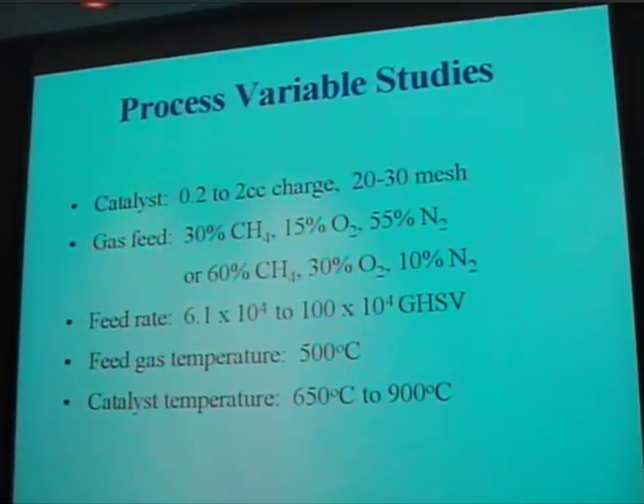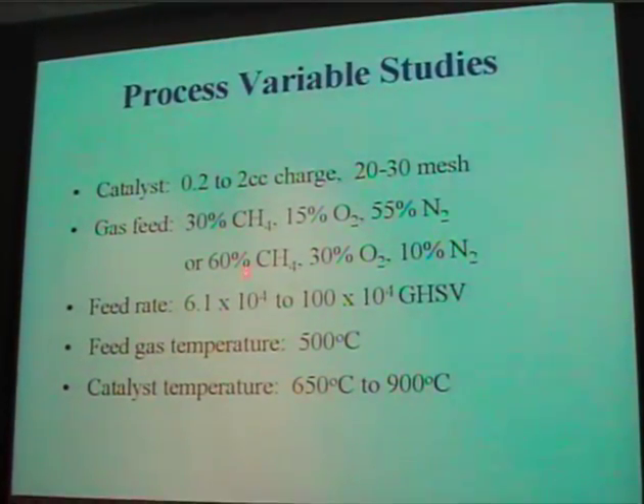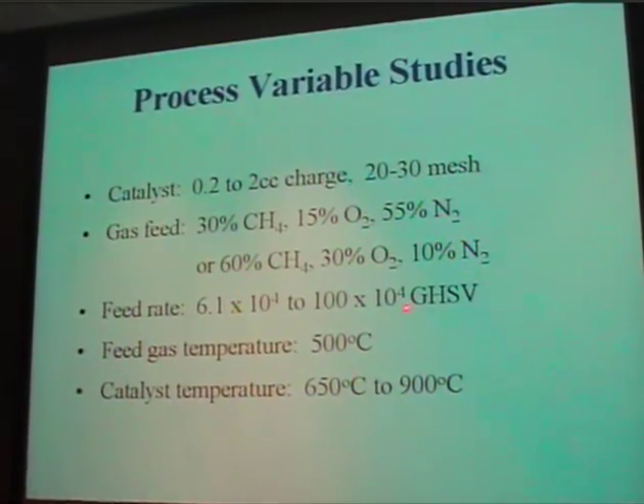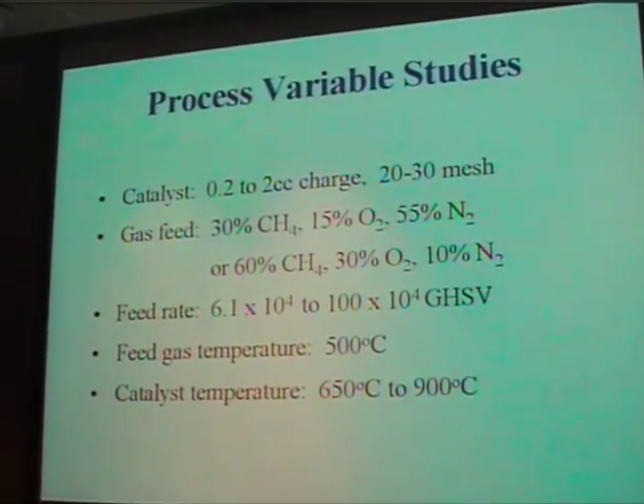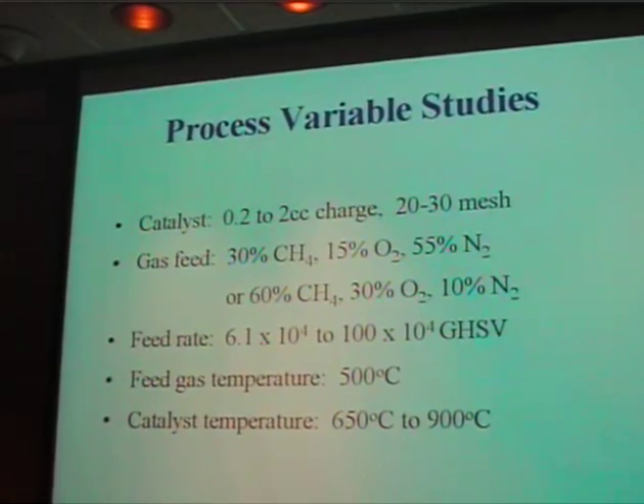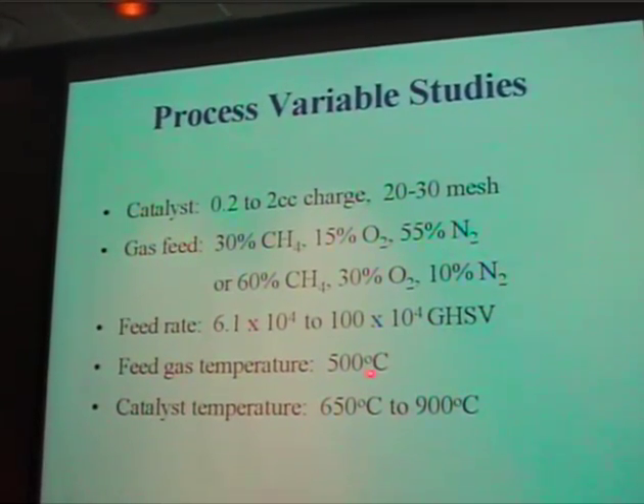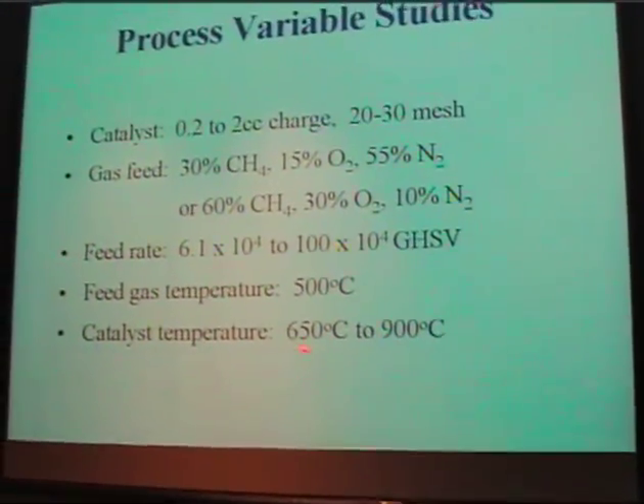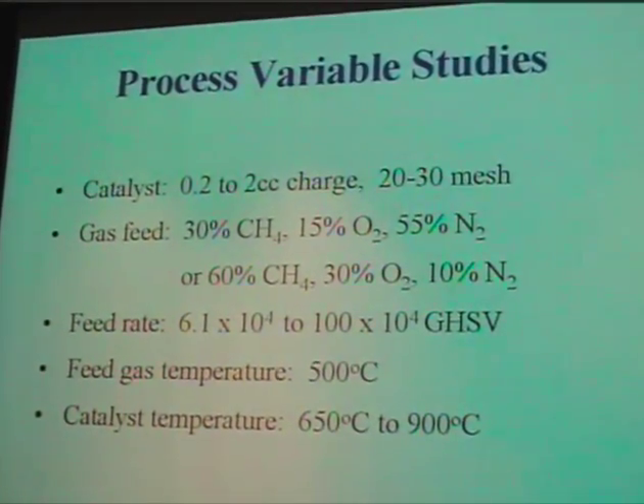So typically when we're doing our screening in the beginning of the program, if you really didn't need a whole lot of catalyst, you could charge anywhere from 0.2 to 2 cc's of a 20-30 mesh material. We had two different feed scenarios that we would run typically, and we could go up to about 1 million gas hourly space velocity. We would preheat the feed to get the reaction going, 500 degrees C. And typically, the catalyst that you'll be hearing about today would run up to about 900. Now, the Group 8 metals, in the work that Lanny Schmidt has published, would light off at higher temperatures and generally operate around 1100 degrees centigrade.